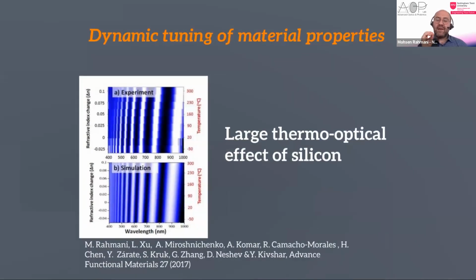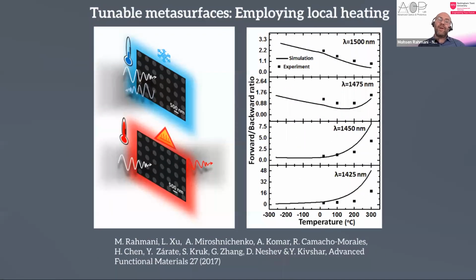But there is one tuning way that can be done only by dielectric metasurfaces, which is employing the thermo-optical effect of silicon. Silicon has a very large thermo-optical effect. It means that when you change the temperature of the silicon, the refractive index of silicon changes. Some other materials like germanium also have it, but silicon has a very large one. And in this paper, a few years ago, we first took a thin film of silicon, and you see these Fabry-Perot modes, and then just by heating it, you can see this nice shift of the Fabry-Perot modes, showing that the refractive index is changing. Then we took this phenomenon and this understanding and used it in metasurfaces, and we made some metasurfaces, targeting some wavelengths and some certain modes, which is published in this paper.